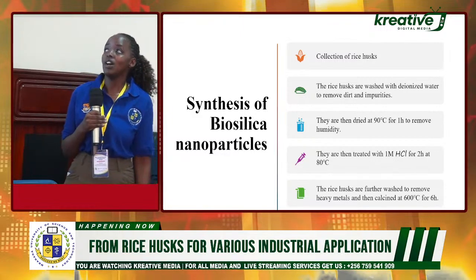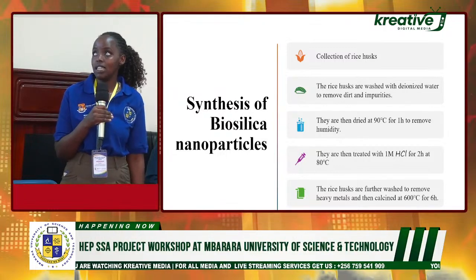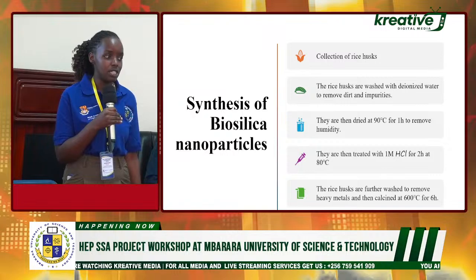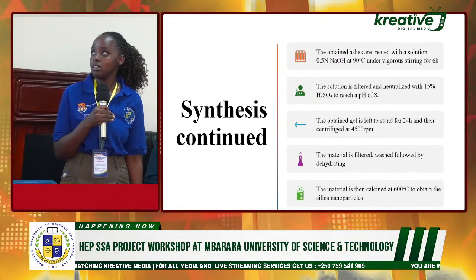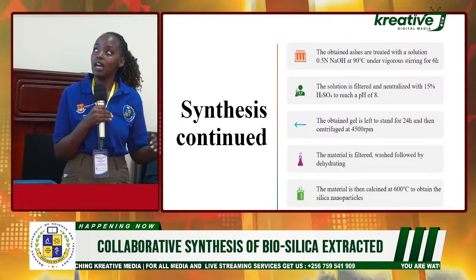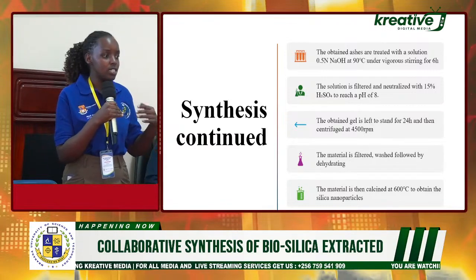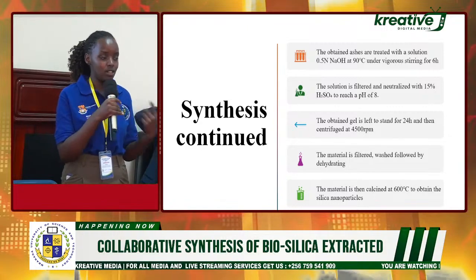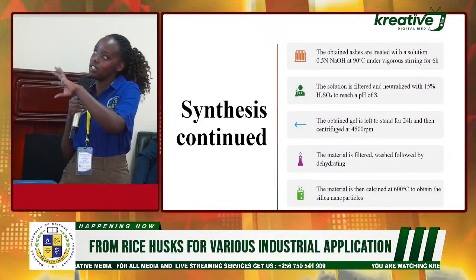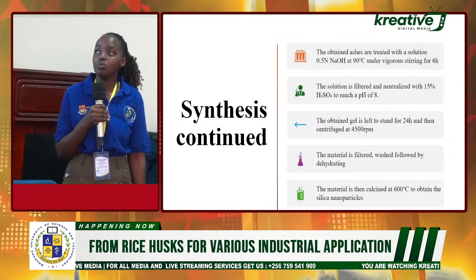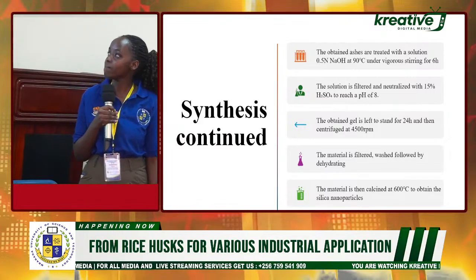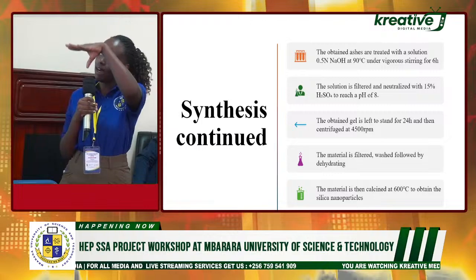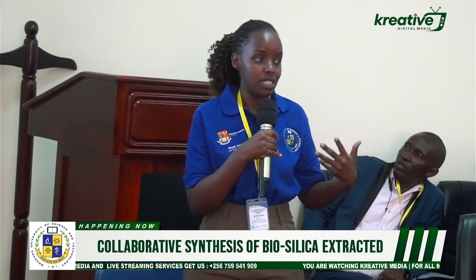Okay. So after combustion, we are going to obtain ashes, and these ashes, as we said, still have impurities. The ash that we've obtained contains silica, silicon dioxide. And we treat these ashes with a solution of sodium hydroxide to produce sodium silicate. And then this solution is filtered, and then the filtrate is titrated with sulfuric acid up to a pH of 8, at which the silica gel precipitates out.